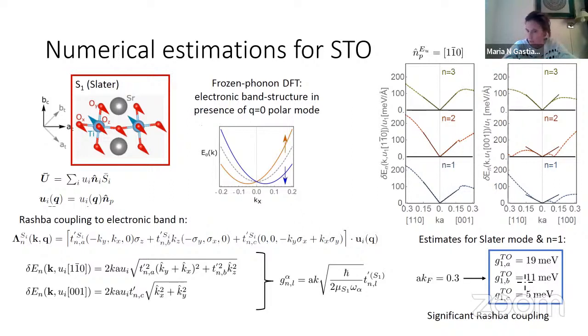to get a feeling of what kind of numbers we're getting, and they are quite significant. They are pretty remarkable. There were some estimations a few years ago saying, let me assume that it is proportional to this inter-site hopping matrix element, and then I'm going to be overestimating this coupling, and what they were getting was 3 times smaller than this. So the first take-home message is that, at least from Ab-initio calculation, it seems like the linear coupling between these electronic bands and the transverse optical phonon polar mode is significant. And now, once I have this, I already worked out the superconducting problem, and I do have the lambda BCS in terms of this G, and then I can get an estimate. So let's now see how that one looks.